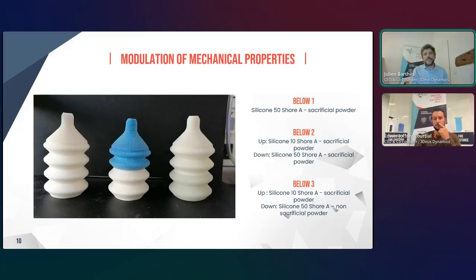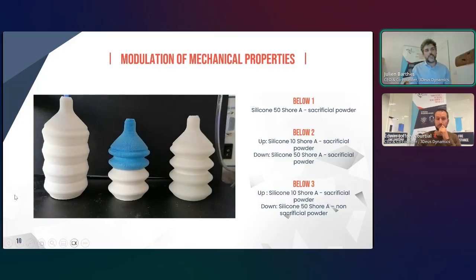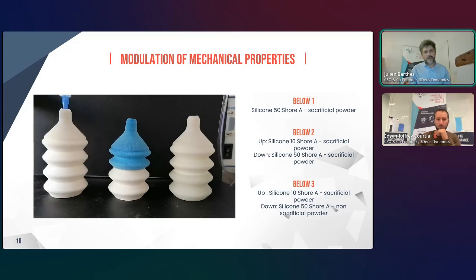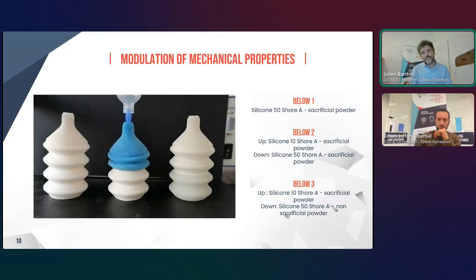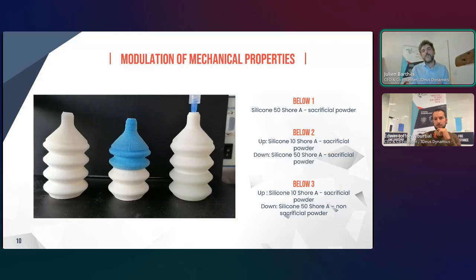Then another way of playing with the properties, you can change the mechanical property almost the way you want. As you can see on this small video, on the left, you have a 50 Shore A silicone, a classical one. Then you can even change the silicone during the process. Bottom part, 50 Shore A, top part, 10 Shore A. Or also, another way, you can change the powder in which you print. You will see on the right, the last one below. Basically, you start with a powder that you will keep in the silicone. You create a composite with almost no elongation. And on top, you have a 50 Shore A silicone in which you have removed the powder.